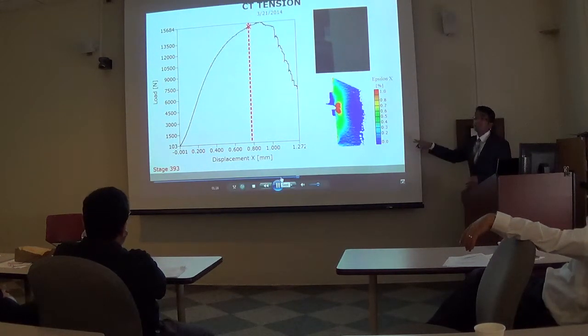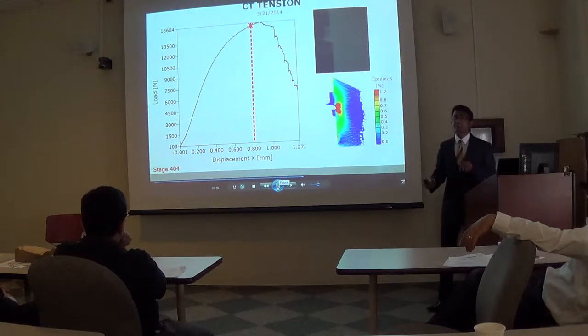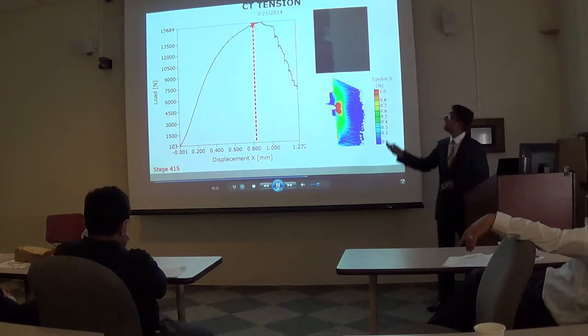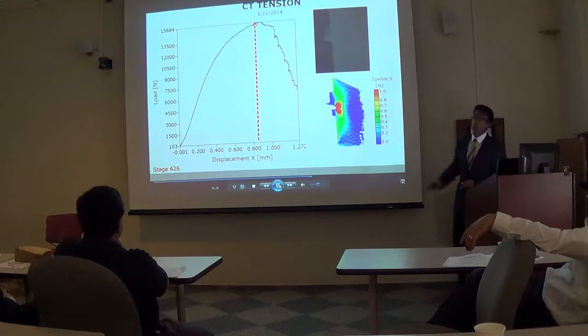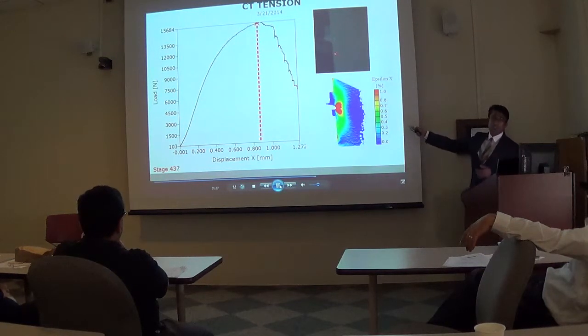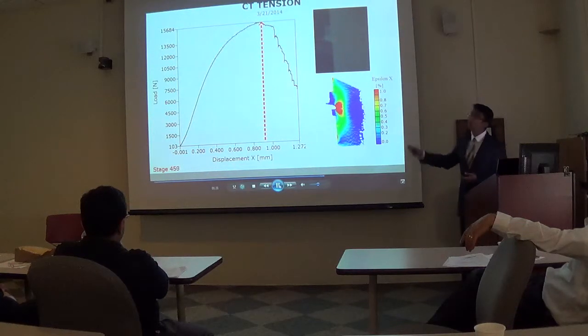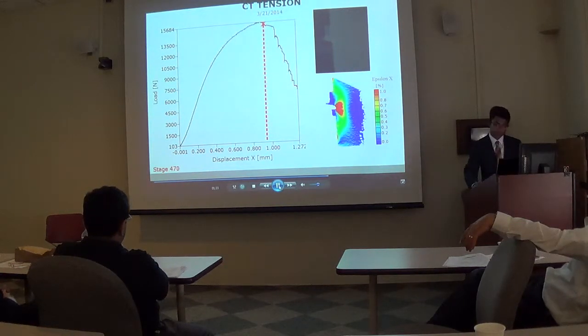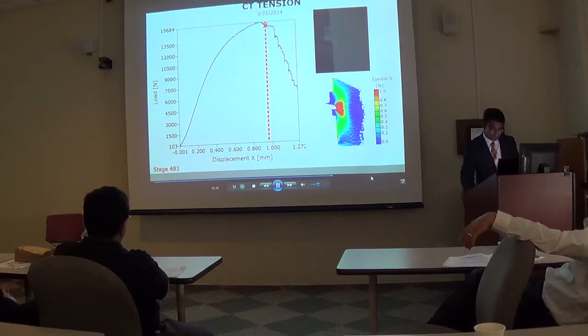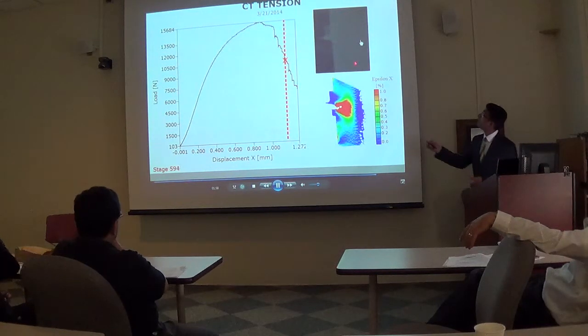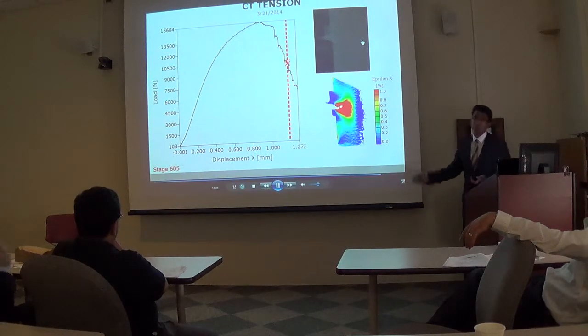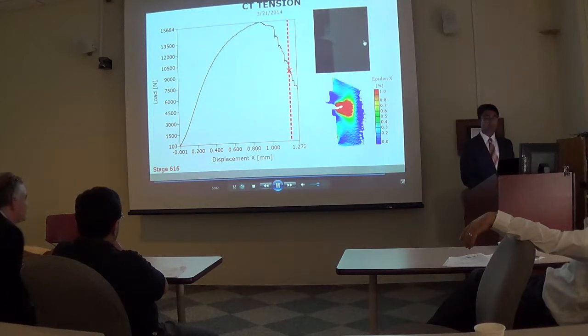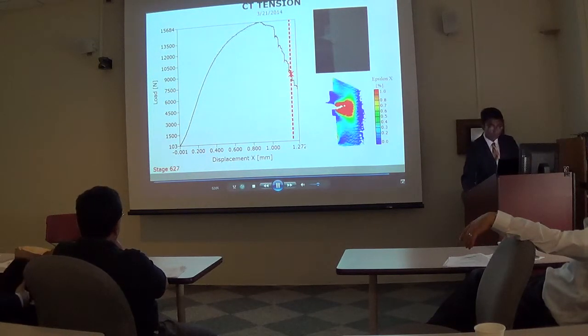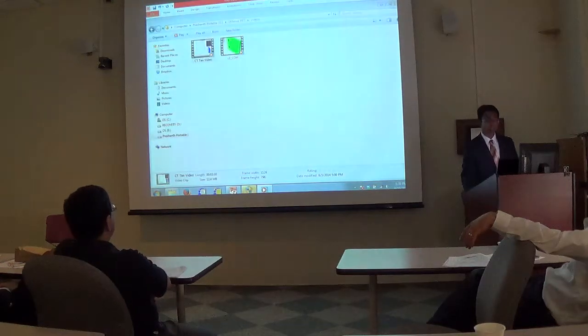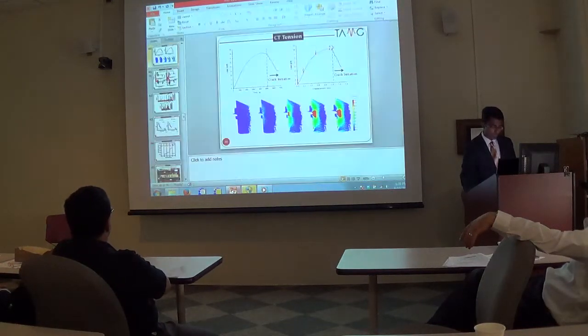Now this full field technique was also utilized to understand exactly when the initiation of cracking happened, the specific load interval, and also the vision. This is an actual visual image that was seen by the naked eye during the test. So you can clearly see exactly at a certain point when you start to see the initiation of cracking. As the specimen is being loaded, you can start to see how cracks were formed, which was also seen with the full field here. So this was utilized to see exactly when cracks were initiated in the specimen.